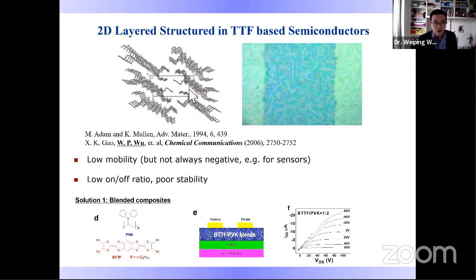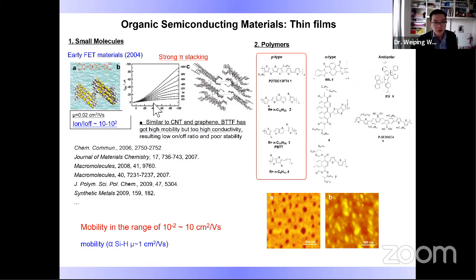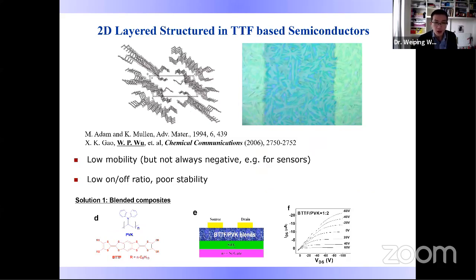However, although we got a relatively high mobility, from this output characteristics we found that it has a very poor on-off ratio. So we were very curious about the reason why it has a relatively low on-off ratio. We have solved this problem through two approaches. The first approach is to blend it with a very low mobility PVK molecule or insulating polymers. We successfully enhanced this on-off ratio and got nice output curves with saturation.